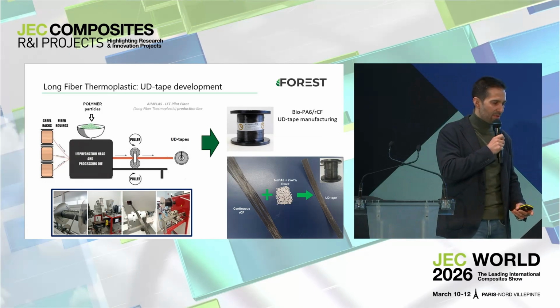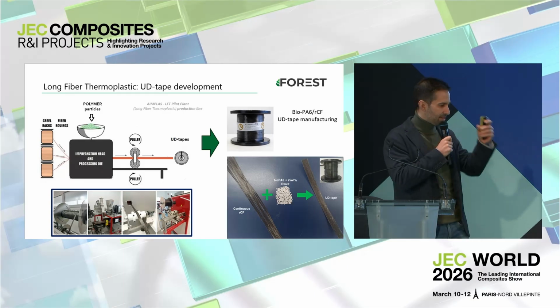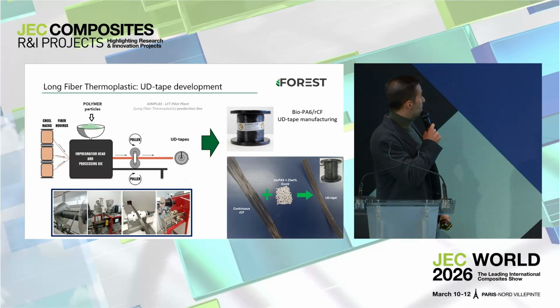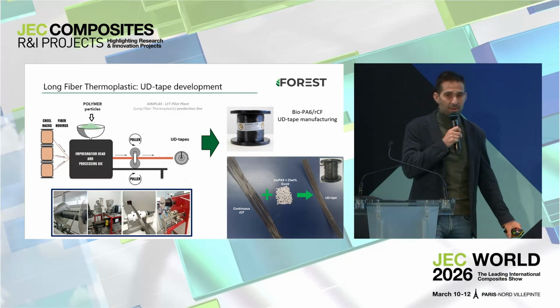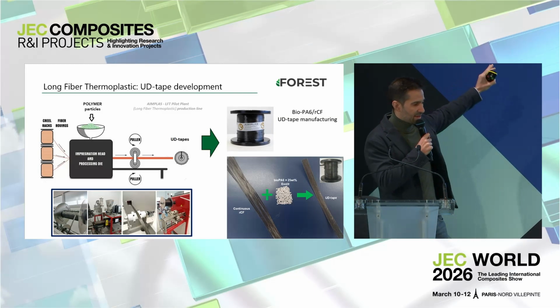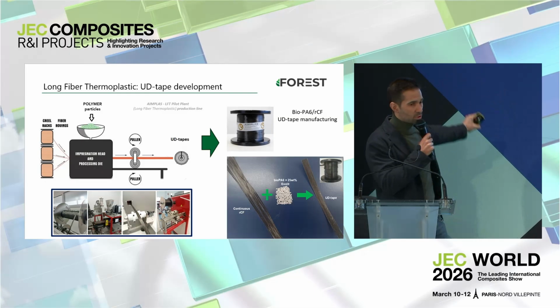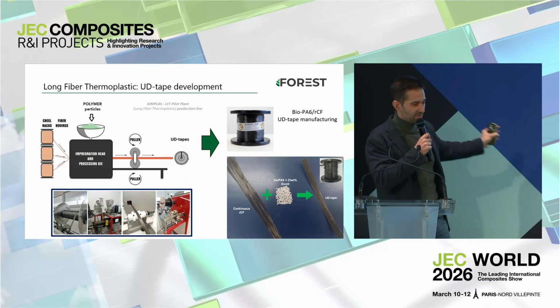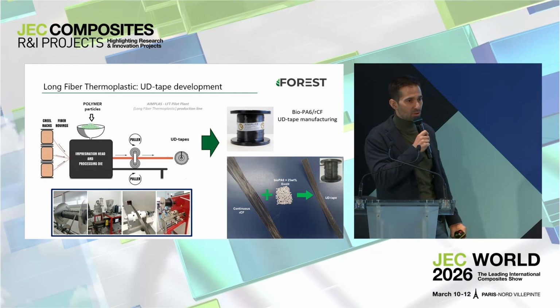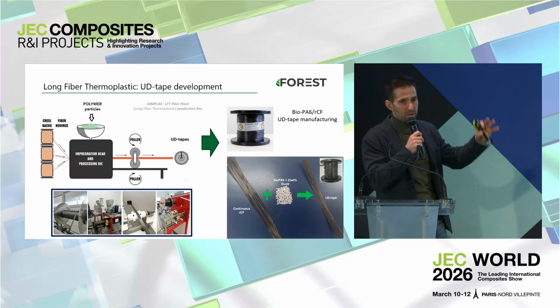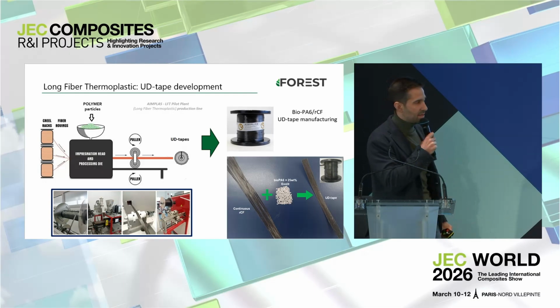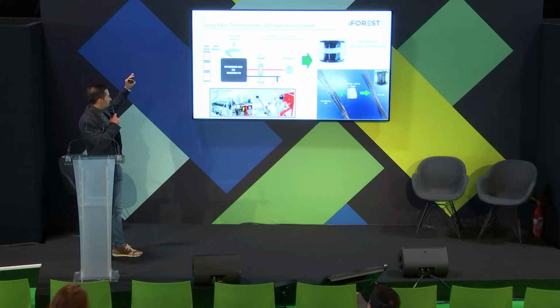Just to give you an idea of the UD tape development, we have this schematic. Basically, it's a long fiber thermoplastic pilot plant, and what we have here is basically a downstream. We have the carbon fiber supply: continuous carbon fiber bobbins, and these bobbins feed the impregnation system. It's a melt impregnation system in which we melt the resin together with the additives, in this case the flame retardant. And then with a series of calenders and pullers, in the end it's a pultrusion system as well. So we obtain this UD tape. We get these bobbins on the right side.